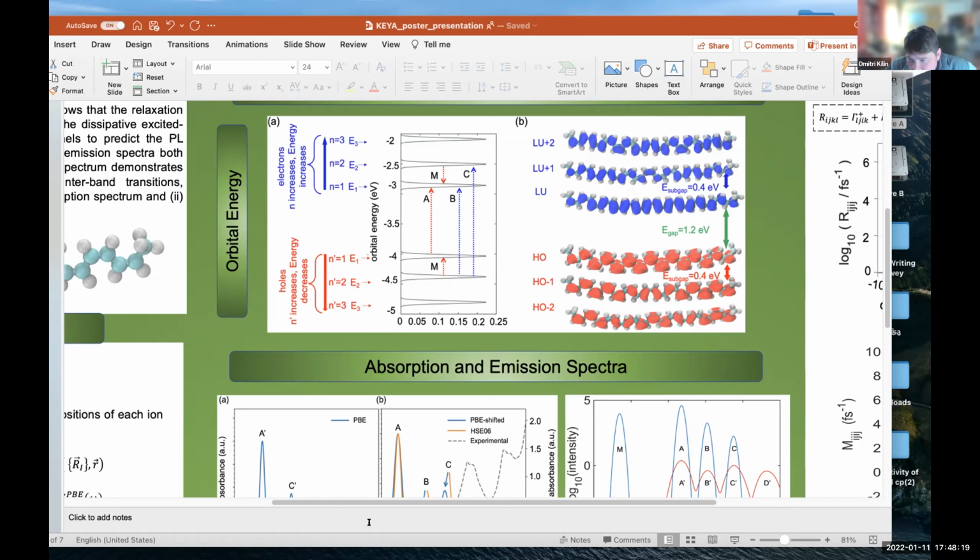Yeah. So the lowest state has one big blob, and the second state has two big blobs. Right? Okay, yeah. And if the system is in the LUMO+1 second state, then there is no density in the middle. Right. Okay. And if you have a transition from LUMO+1 to LUMO, then density condenses from these edges outside to the center.